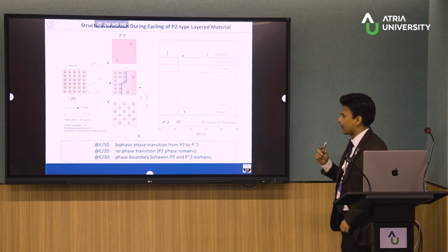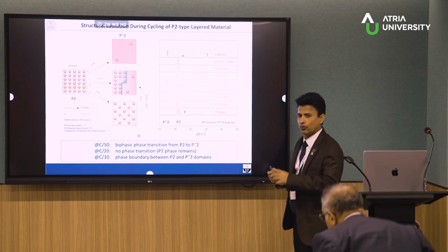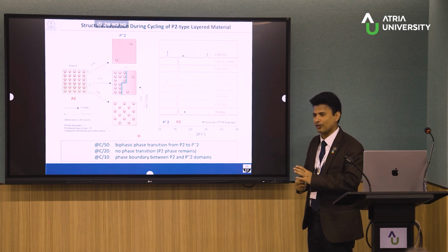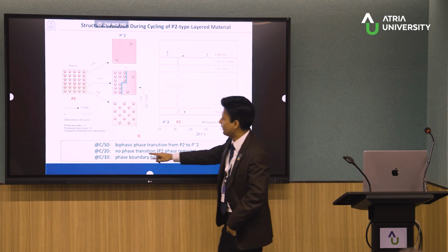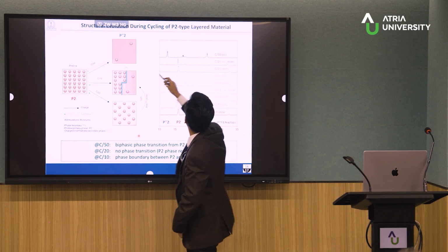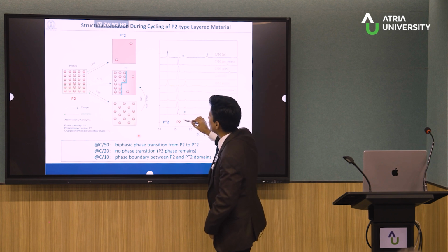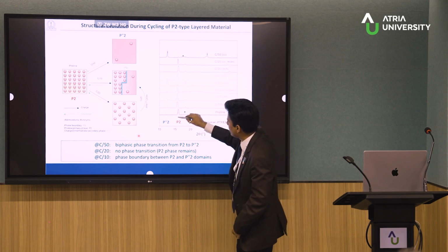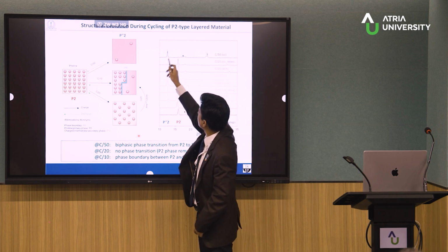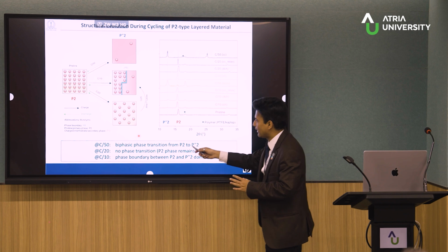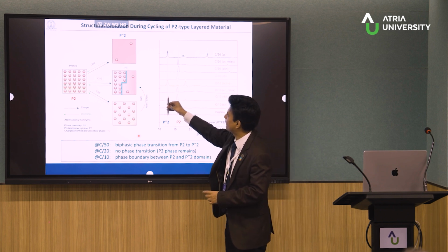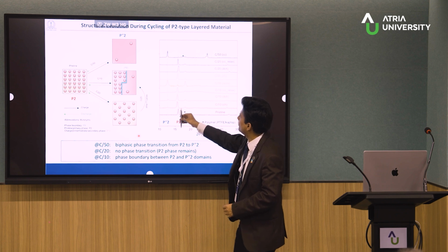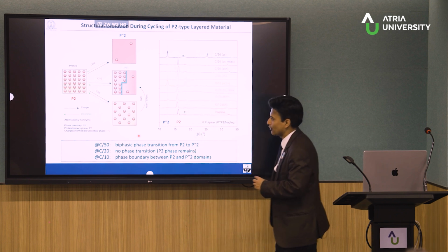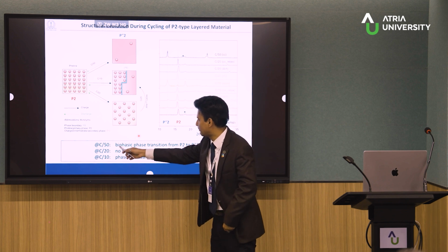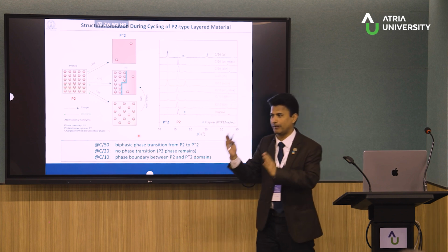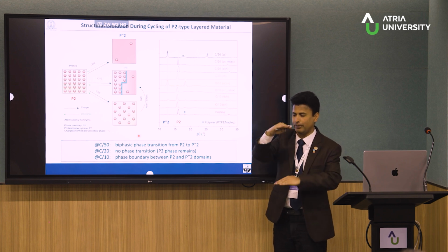Now I want to summarize all the things we do. When we do the charge discharge of this anionic material at a very slow rate, C/50, what happens? We saw this is our initial P2. You see the large P'2 peak here, two dotted lines. So when we do C/50, all the P2 became P'2. Pretty much when we do C/50, there is a biphasic transition from P2 to P'2, a 100% transition from P2 to P'2.